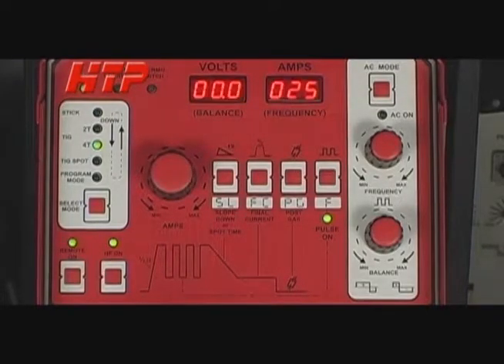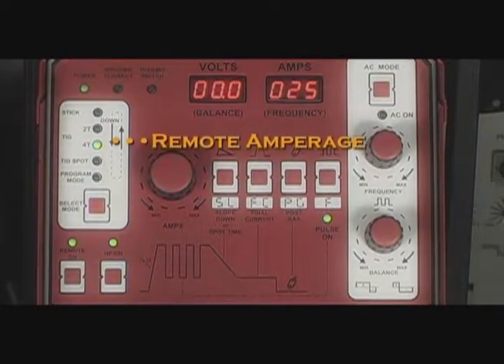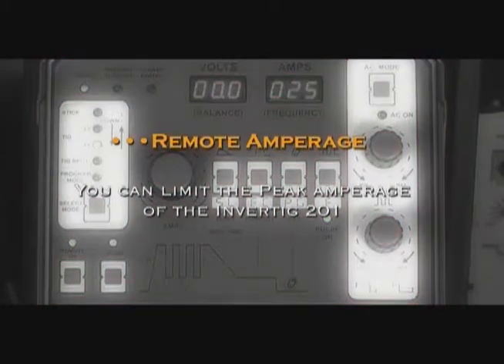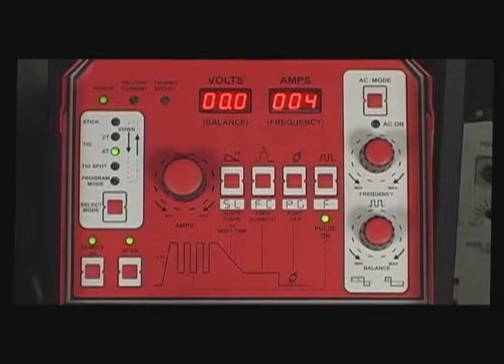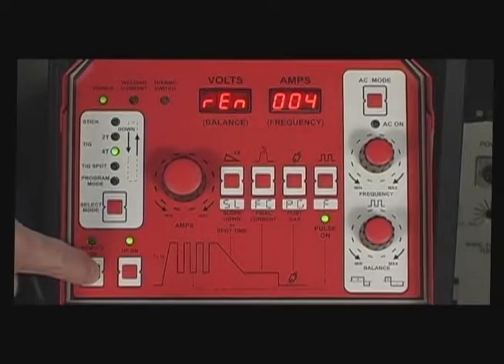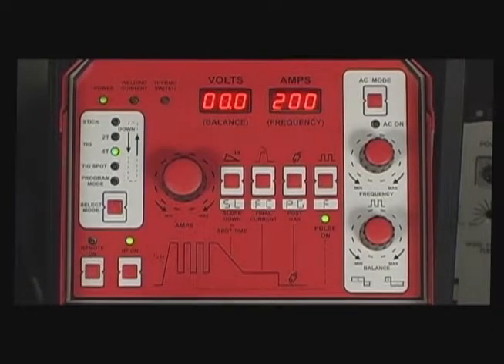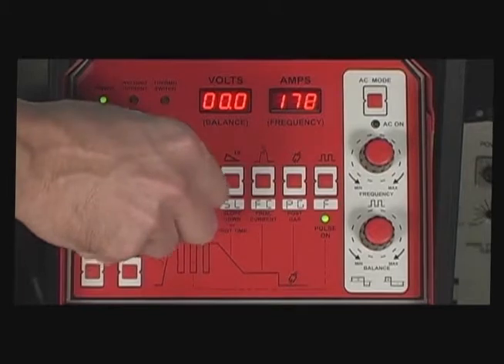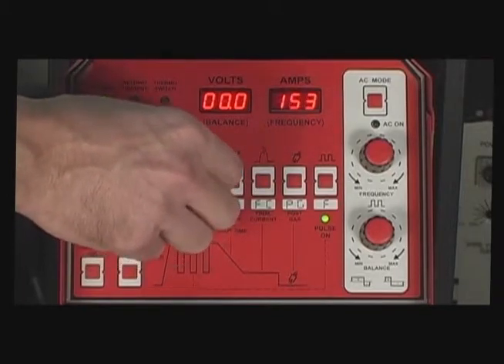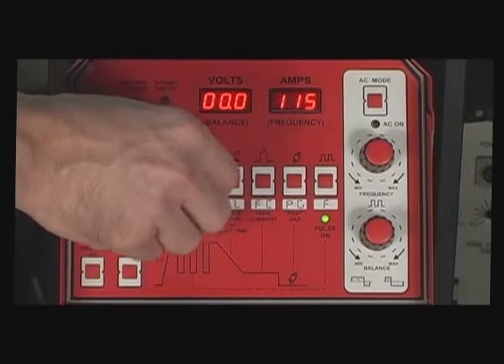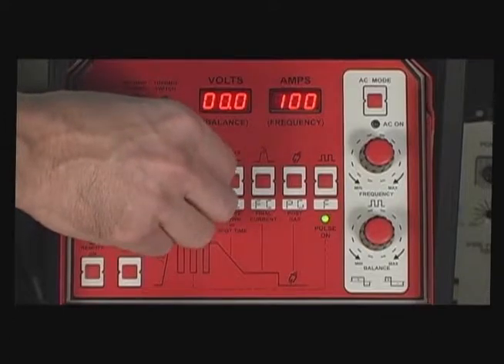It is possible to limit the peak or maximum amperage of your 201. To limit the amperage of the machine to 100 amps, depress the remote on button for 5 seconds until the green indicator lamp turns off. You will see 200 amps in the display, which is what the machine is currently set to. Using the amperage adjustment knob, adjust the amperage to 100 amps.